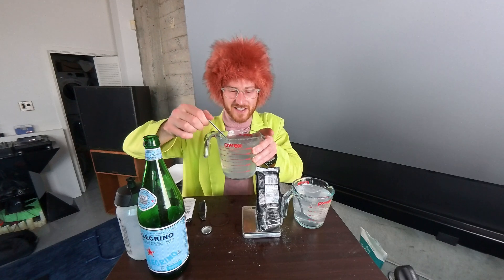There are a few ways we can test that hypothesis. If we add more sodium alginate to the Pellegrino, can we cross some threshold until it really turns into a gel? Another approach is altering the pH — see if we can get it to the environment best for gelling, which is between pH 3.5 and 4.5. And another is lowering the water content so we have a much higher concentration of sodium alginate and pectin compared to the total amount of water.